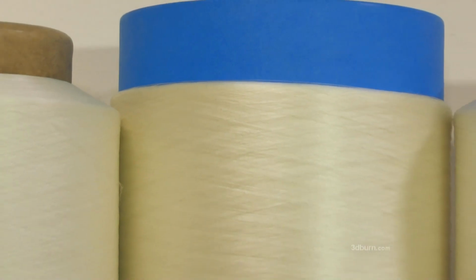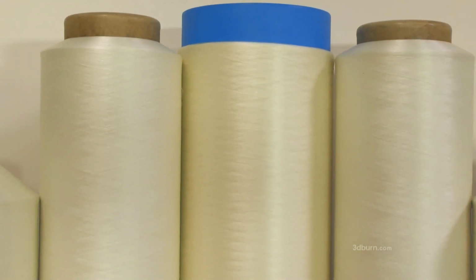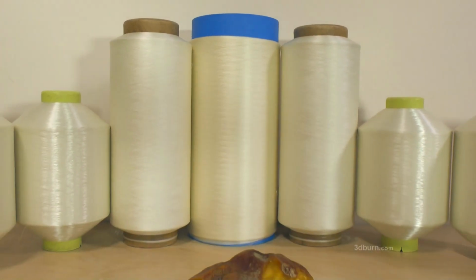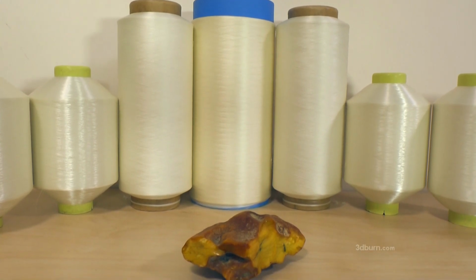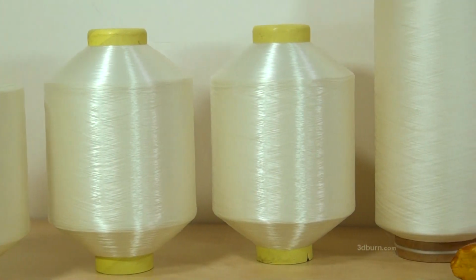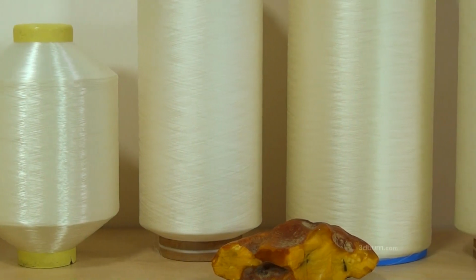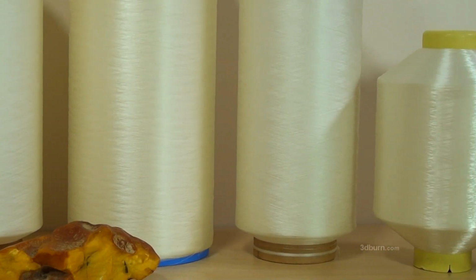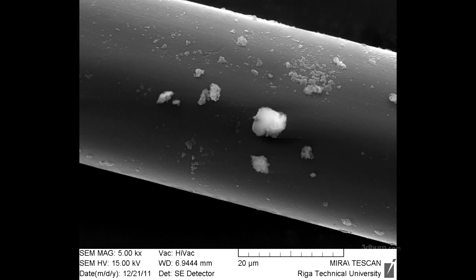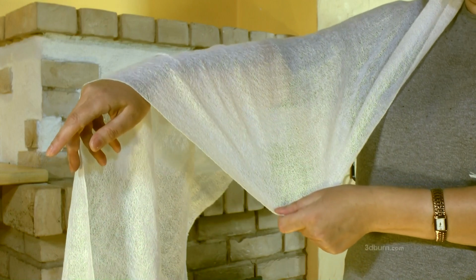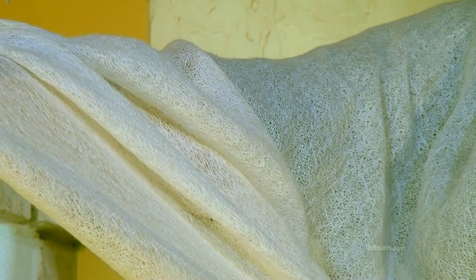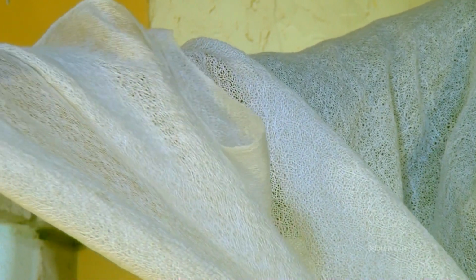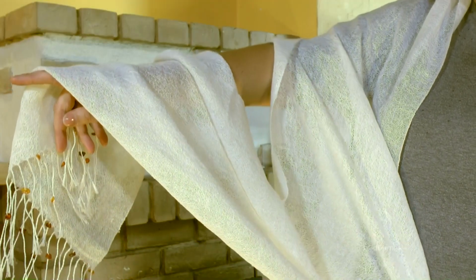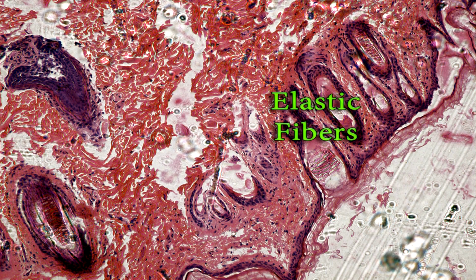The developed two-step technological manufacturing process enables us to receive amber threads with evenly distributed technologically processed succinite and provides the necessary strength characteristics of the thread. A new product type was developed, amber composite threads, with a significant advantage compared to other known polymer composite threads. Composite threads with a smooth surface that does not cause allergic reactions, stimulate the activity of the skin, promote normal skin area regeneration, reflect ultraviolet rays, and prevent the formation of clots in contact with platelets, with biocompatibility with living tissue. In addition, technologically processed succinite activity lasted longer than 1 year.